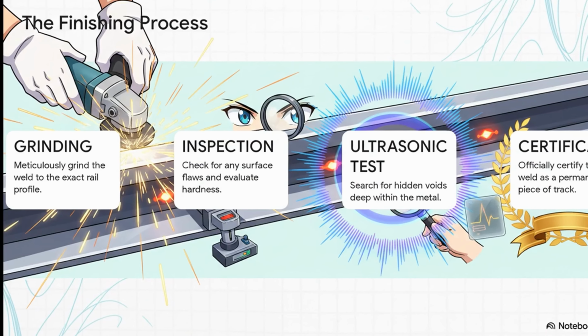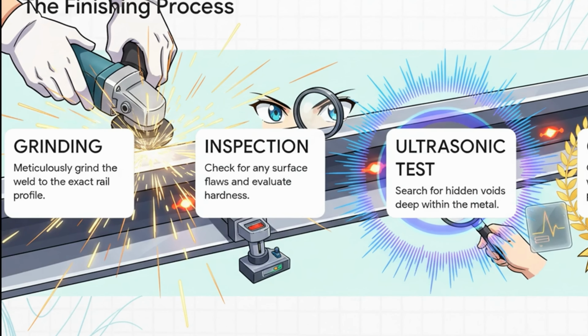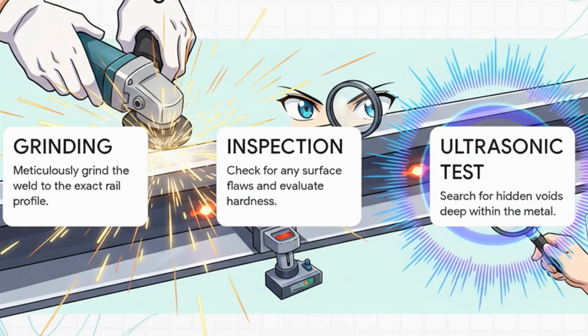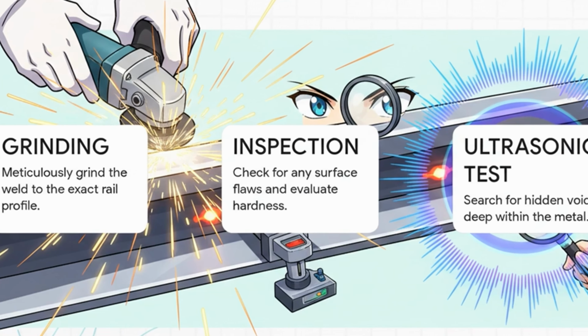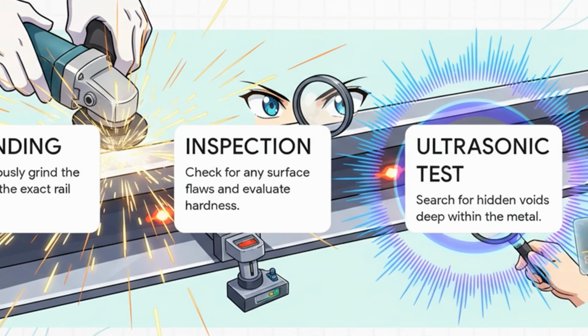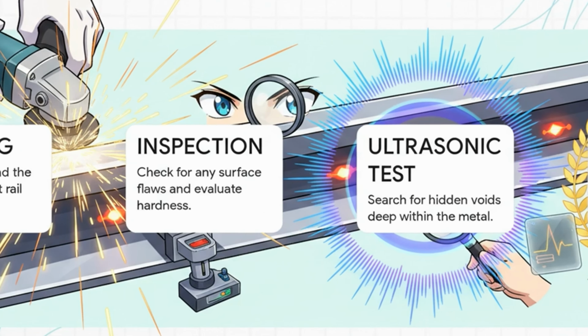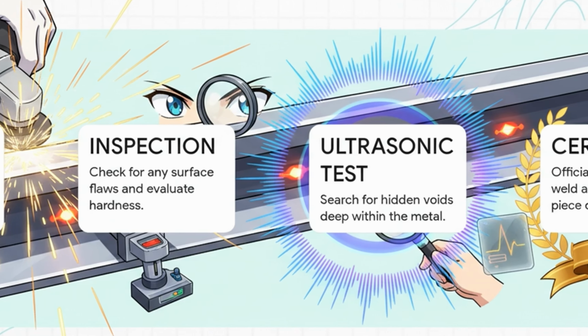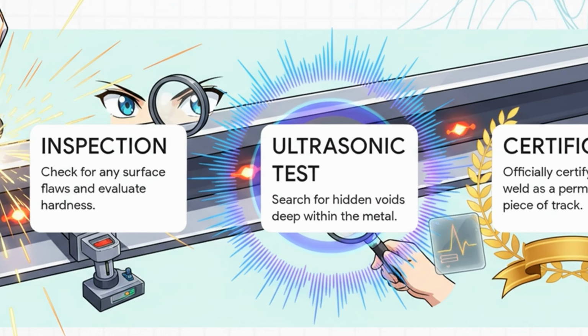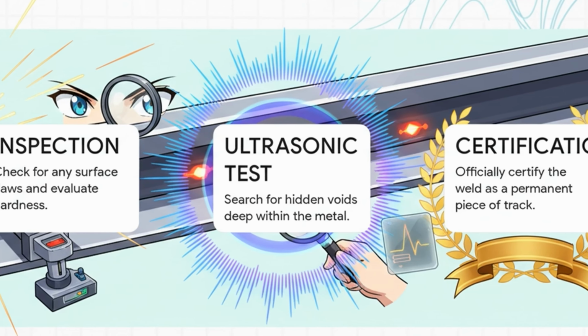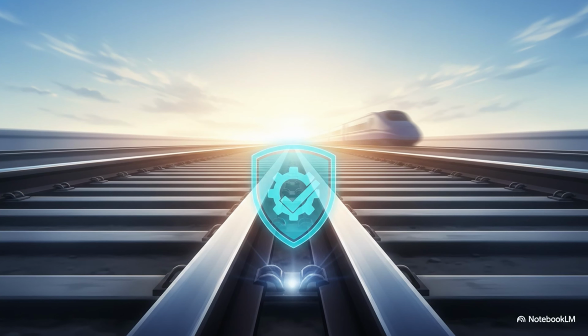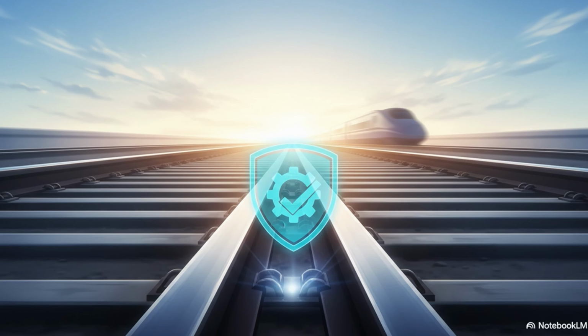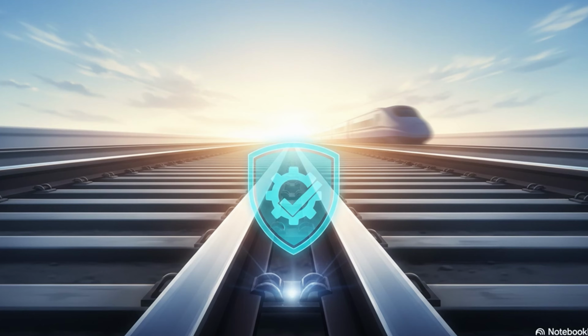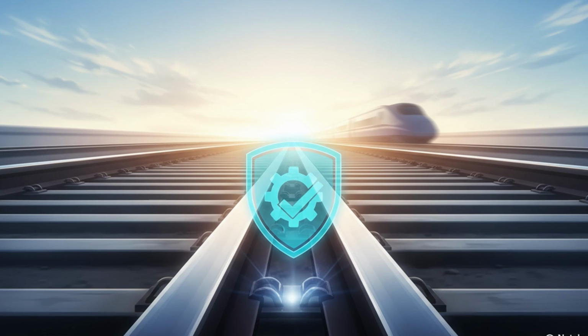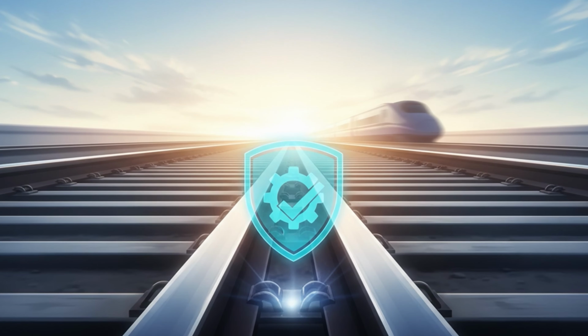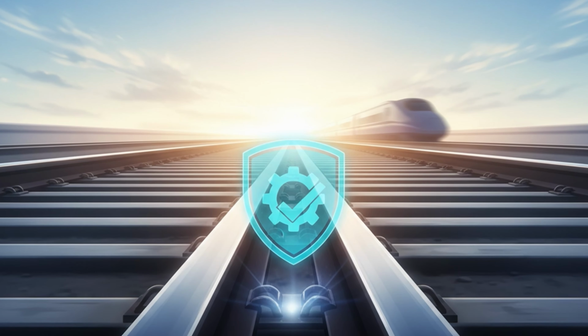So to make absolutely sure the weld and that tricky HAZ are perfect, the joint has to pass one last rigorous exam. It gets meticulously ground down to match the rail profile exactly. Then it gets a visual inspection for any surface flaws, followed by hardness tests, and finally they bring out the high-tech gear, ultrasonic testing, which uses sound waves to hunt for any hidden voids or imperfections deep inside the metal. And after all that, all the fire, the precision, the microscopic engineering, that brief, violent burst of chemistry is now officially certified. It's a seamless, permanent part of our critical infrastructure, ready to handle millions of tons of traffic.